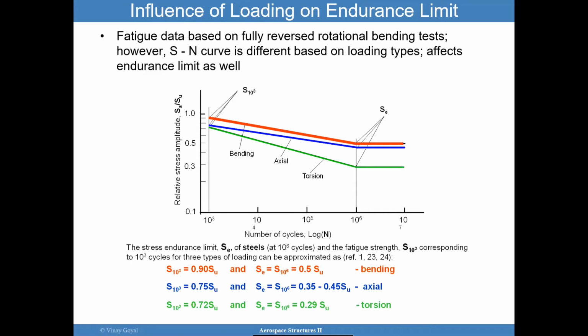So there is an influence of the loading on the endurance limit. Fatigue data based on fully reversed rotational bending tests show that you get different behavior. For a bending test, you get a little more benign behavior. If you go axial, the condition worsens a little bit. And when you go to torsion, you take a lot more of a hit. So it's important to understand that depending upon your situation, the endurance limit can change depending upon the loading.